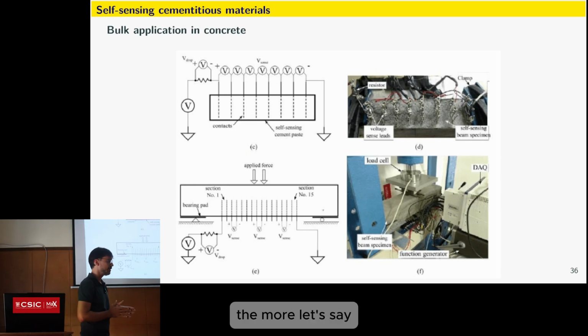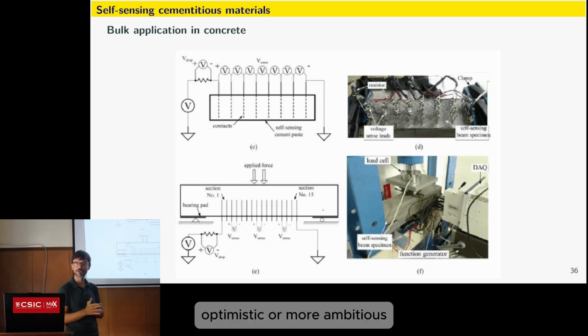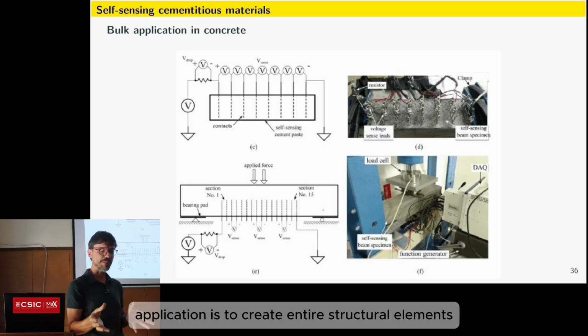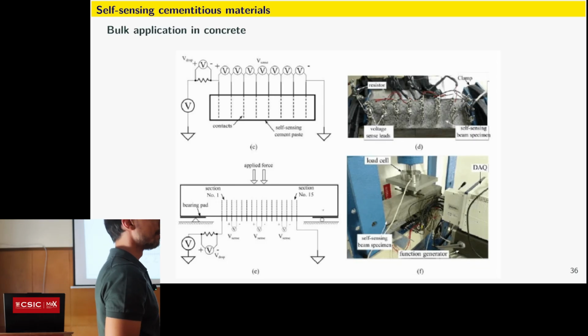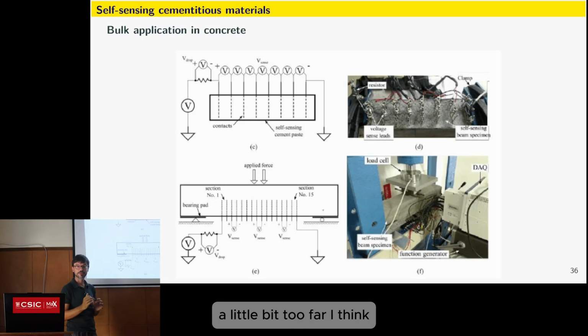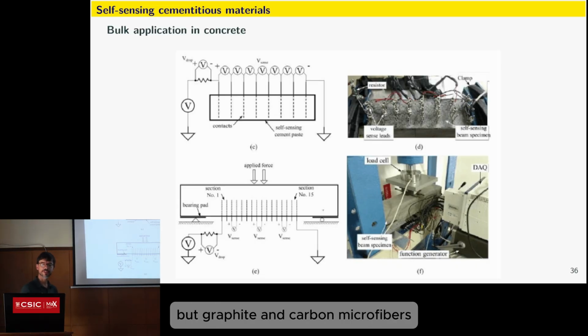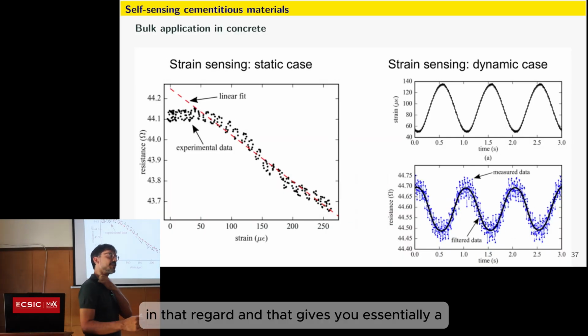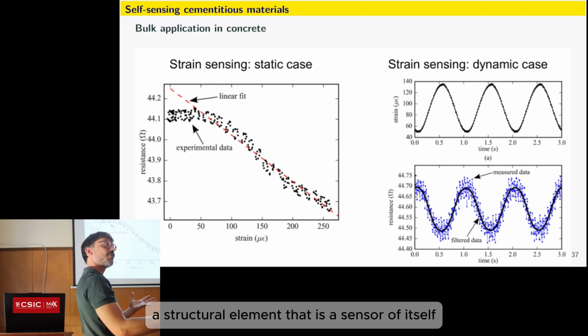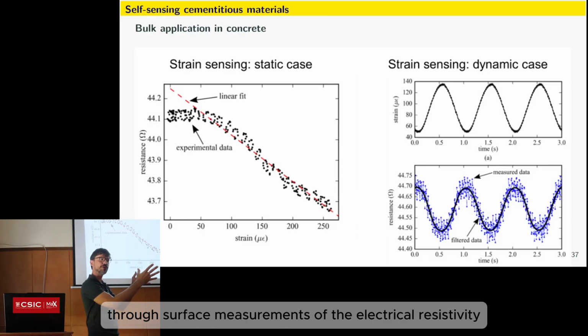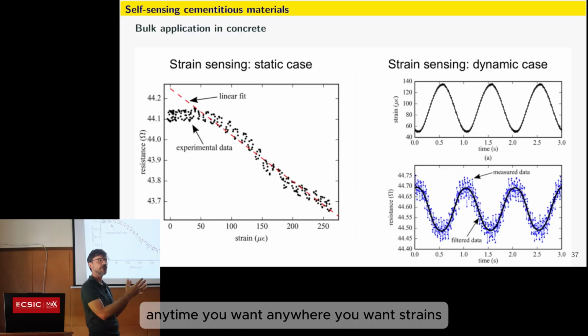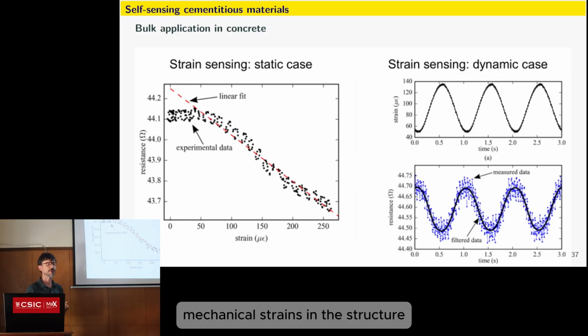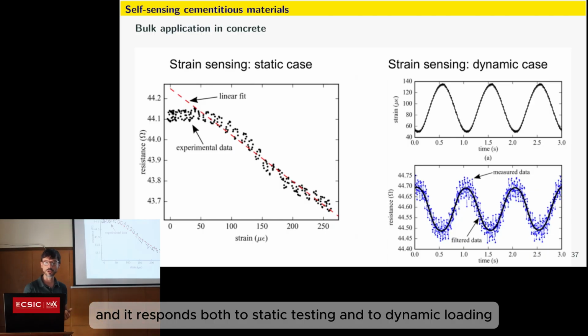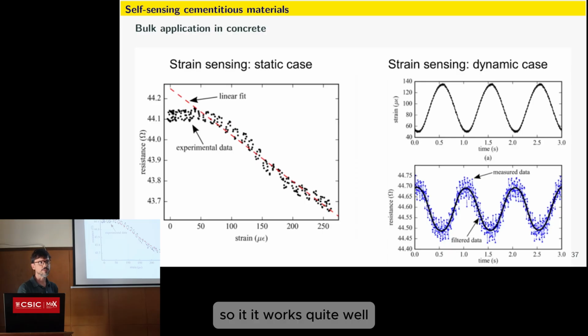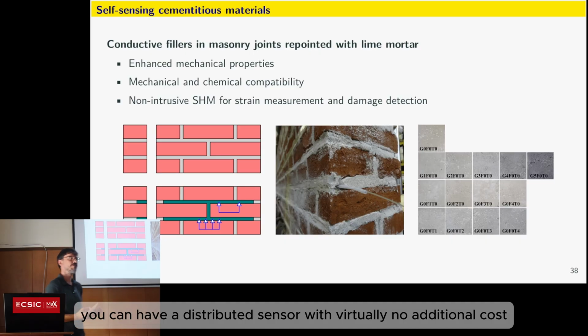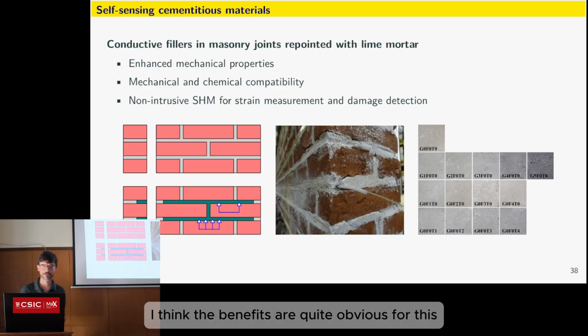The more, let's say, optimistic or more ambitious application is to create entire structural elements out of these modified materials. Carbon nanotubes would be pushing it a little bit too far, I think, but graphite and carbon microfibers work quite well in that regard. And that gives you essentially a structural element that is a sensor of itself. You can measure through surface measurements of the electrical resistivity anytime you want, anywhere you want, mechanical strains in the structure. And it responds both to static testing and to dynamic loading or cyclic loading. So it works quite well. You can have a distributed sensor with virtually no additional cost. I think the benefits are quite obvious for this.